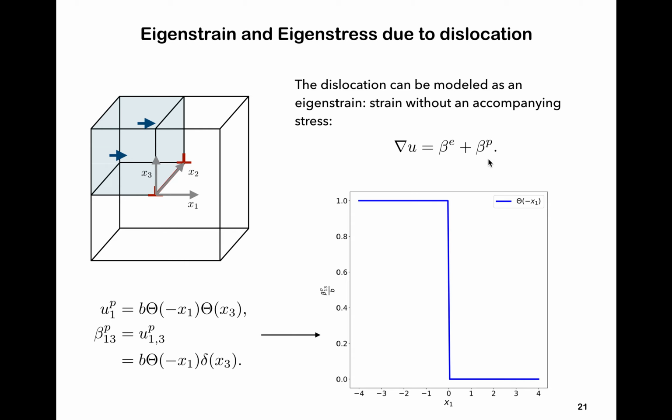And the rationale behind this is what we saw just now. If you were to model your body as a crystalline solid, then you see that plastic deformation is in fact the jump of the system from one stable energy well to another stable energy well, and once it jumps, the behavior in the new well is still elastic, but the total strain has to be summed up as the sum of the elastic part and the plastic strain involved in jumping from one well to the other.